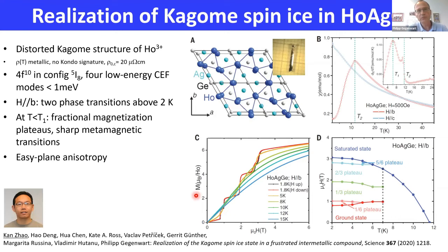The crystal structure of holmium silver germanium is shown here. It's a layered material where we have these stacks of a distorted Kagome lattice of holmium 3+ ions, and it is an intermetallic compound with a temperature dependence of electrical resistance which indicates metallic behavior. There is no signature of Kondo scattering, and there is a nice degree of perfection, and the residual resistance is as low as 20 microohm centimeter.